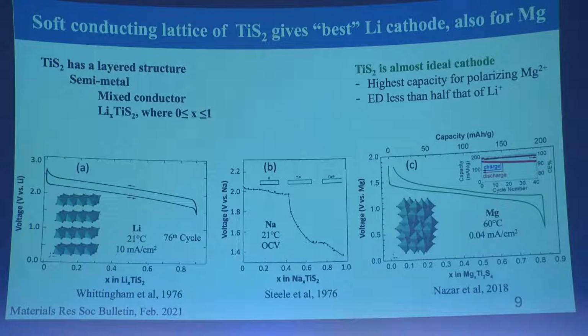In the middle, I show you the example of sodium. Sodium goes in just as easily, but now sodium is bigger. So it has to get those layers and pull them apart to go in. That takes energy. So now we see we've got 2 or 3 separate phases formed depending on the sodium concentration, and you see the voltage drops dramatically. So there's very little interest in these particular sulfide materials. For sodium batteries, for layered oxides, there's still some interest.